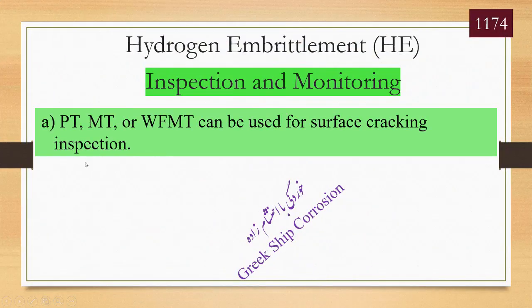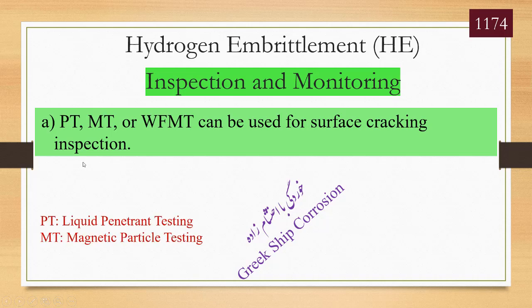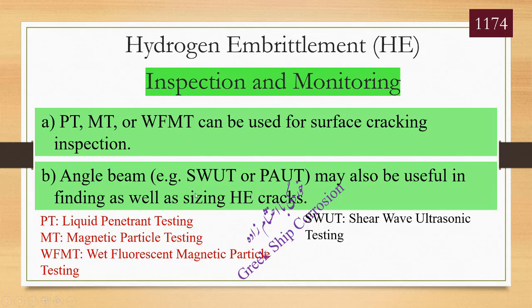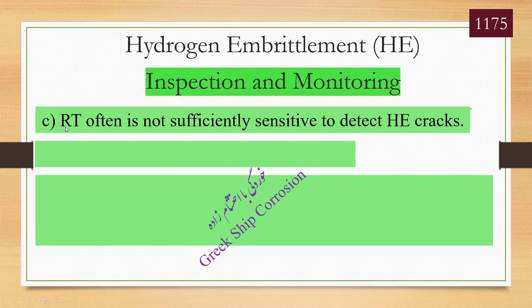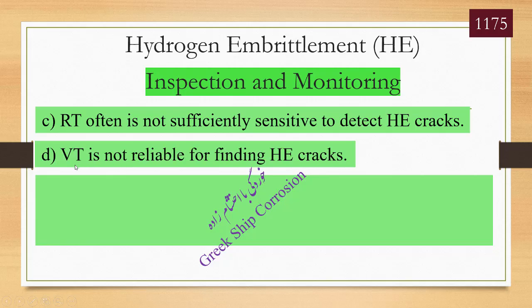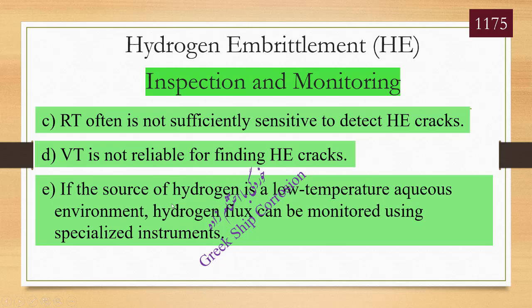Inspection and monitoring. A. Liquid penetrant testing, magnetic particle testing, or wet fluorescent magnetic particle testing can be used for surface cracking inspection. B. Angle beam, for example shear wave ultrasonic testing, or phased array ultrasonic testing may also be useful in finding as well as sizing hydrogen embrittlement cracks. C. Radiography testing often is not sufficiently sensitive to detect hydrogen embrittlement cracks. D. Visual testing is not reliable for finding hydrogen embrittlement cracks. E. If the source of hydrogen is a low-temperature aqueous environment, hydrogen flux can be monitored using specialized instruments.